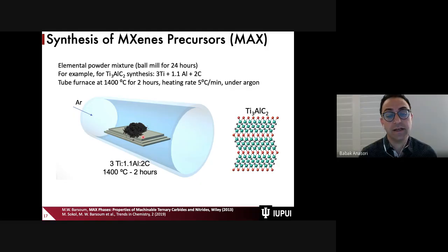Then we put it in a controlled environment in a tube furnace at a certain temperature, usually between 1400 and 1700 degrees C, and hold it for the required time. For this particular material, it's only 2 hours. Then we cool it down, and with reactive sintering, we get Ti3AlC2, this structure. So we go from elemental powders to this structure. We don't do anything else. We just take it to the temperature and conditions at which this material becomes thermodynamically stable, and then we let thermodynamics control the reaction and form the desired material.